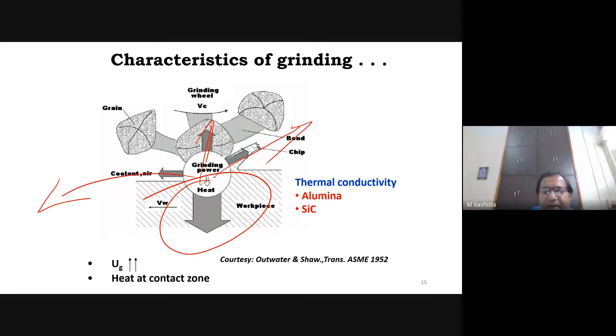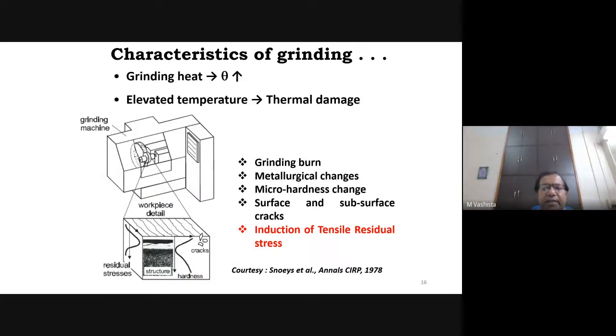Abrasive grit, typically we use alumina or silicon carbide, and they have poor thermal conductivity. The thermal conductivity of alumina and silicon carbide is poor, so they will not take a large amount of heat. Very little heat will be transferred into the abrasive. Hence, the large amount of heat that is transmitted into the workpiece will damage the workpiece detrimentally. And this grinding heat will cause generation of elevated temperature in the form of thermal damage.